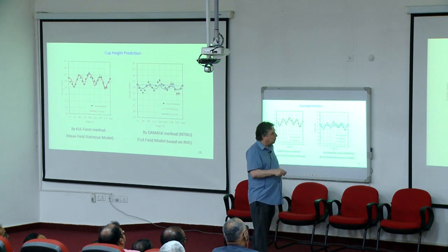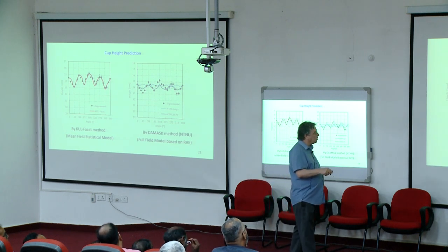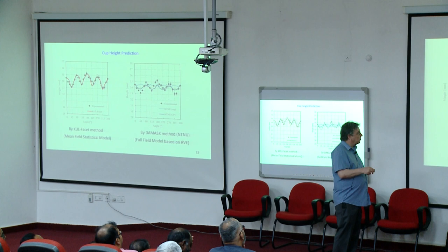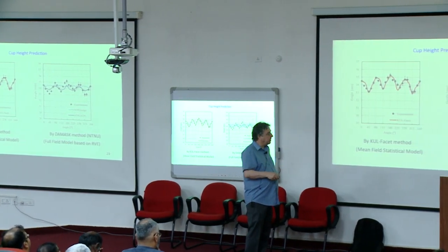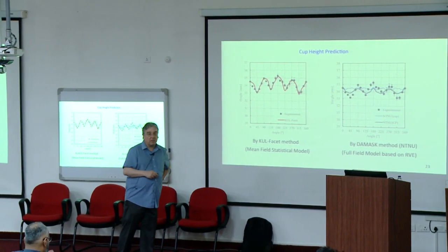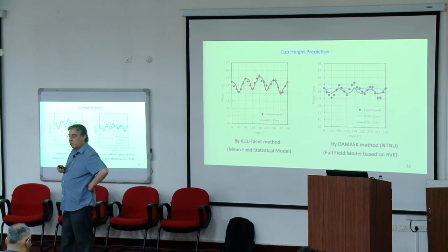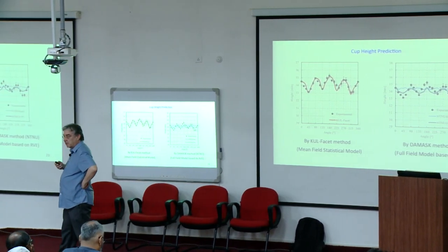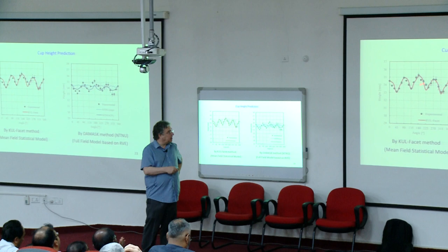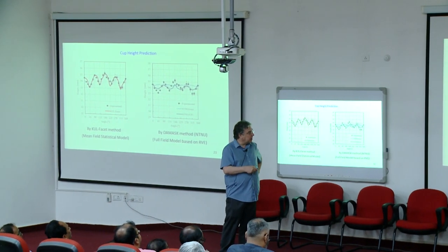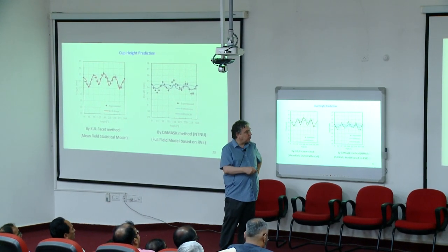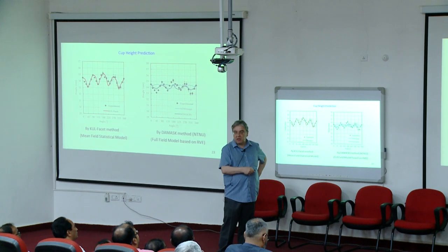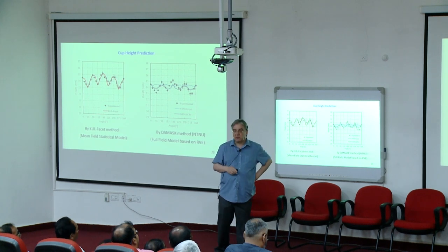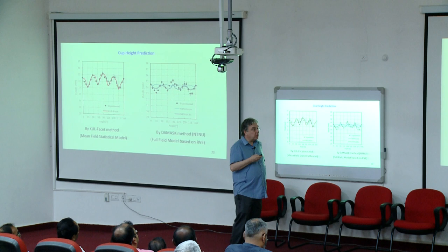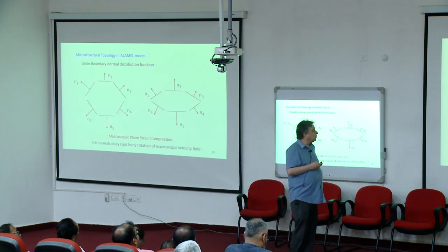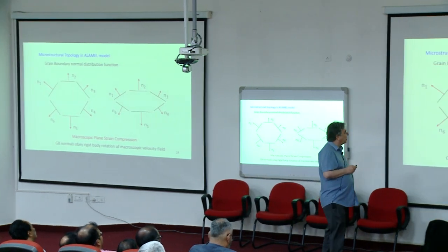And we were, at least in this case, I'm not going to generalize this, even more precise than a full crystal plasticity simulation based on RVEs. Mind you, even if these were equally correct, this again would take weeks of CPU time, and this less than an hour. So that's really an important, powerful way of dealing with microstructure.